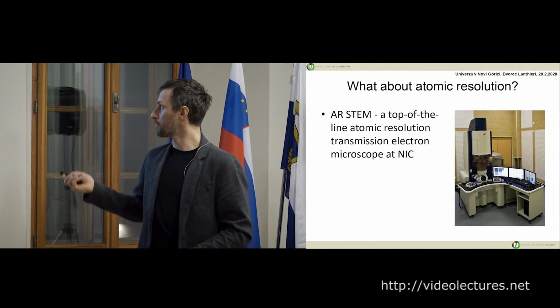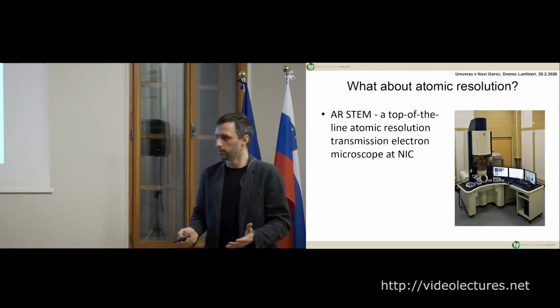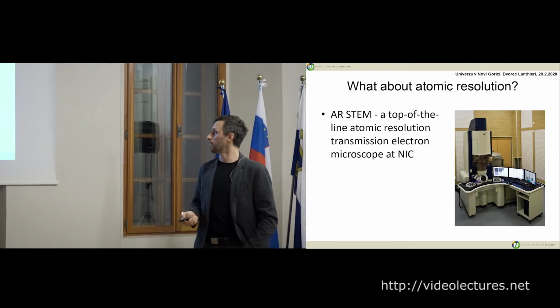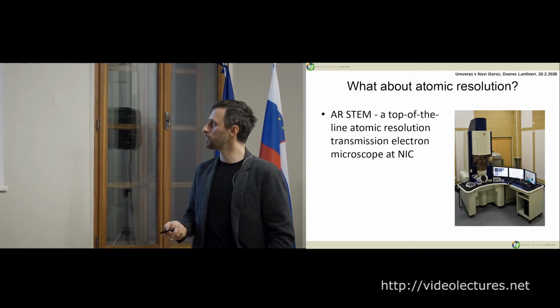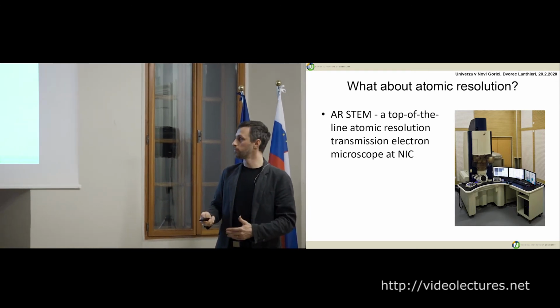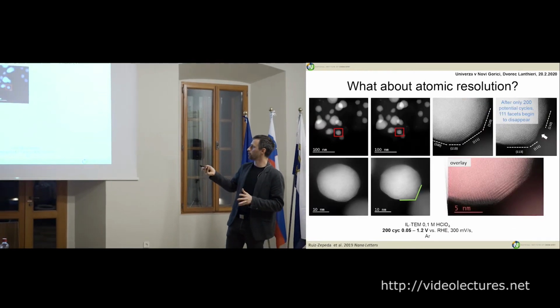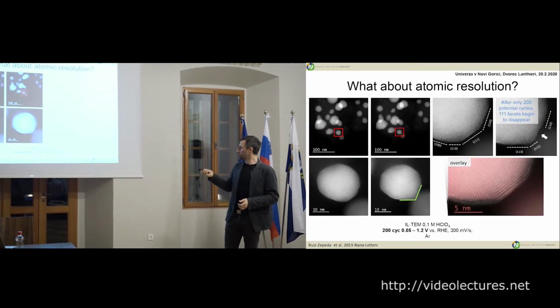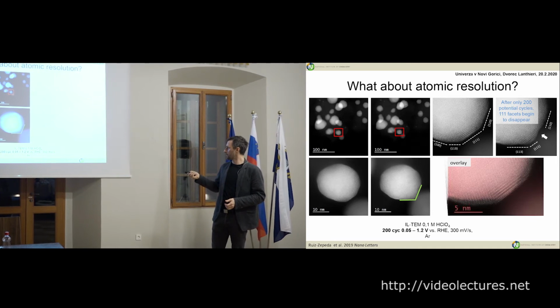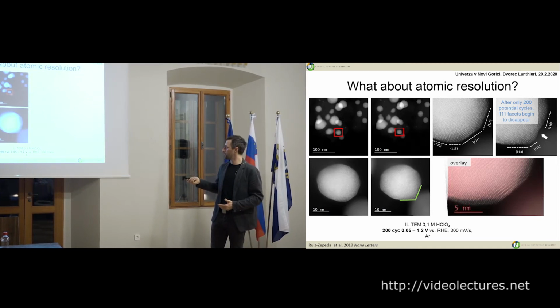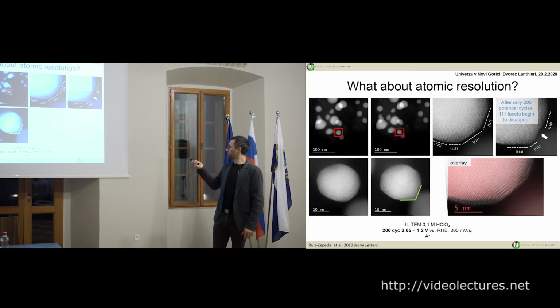Then of course, because we have this nice microscope, we should ask ourselves what's happening on the atomic level. Of course, we just repeated the experiment, did a mild treatment. In this resolution you don't see any difference, but if you zoom in you can see something is starting to happen. It's familiar with the shaping. And if you look even closer, you see the atoms, and you can recognize the facets, because you see the atoms, you can see that the 111 facet is getting smaller.